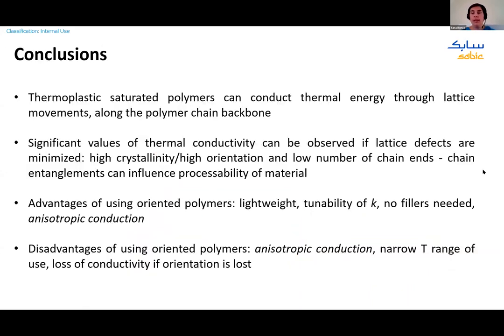So to conclude, thermoplastic polymers can conduct thermal energy through lattice movement, but this only happens through the polymer chain backbone. So if you want to improve this thermal conductivity, you need to reduce the lattice defects. So you need to have high orientation, high crystallinity and a low number of chain ends. You also need to be mindful that chain entanglements in your material can influence a lot the processability of the material and its orientability.